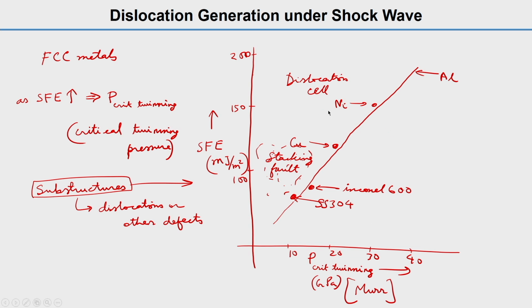But then again, if you go on the other side, the right side of this line, you will end up with twin. At high pressure you will get twin, and for lower pressure you may get the twin faults. So, whether this twin or twin faults will fall here or here, dislocation cell or stacking fault, this is just to show you what the different substructures are at different values of stacking fault energy with critical twinning pressure. We are talking here about shock induced substructures.